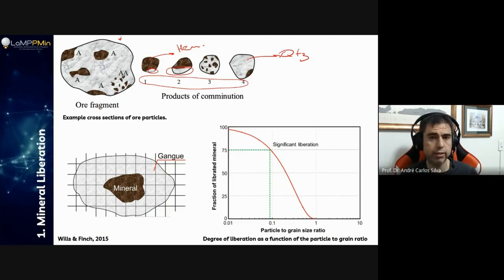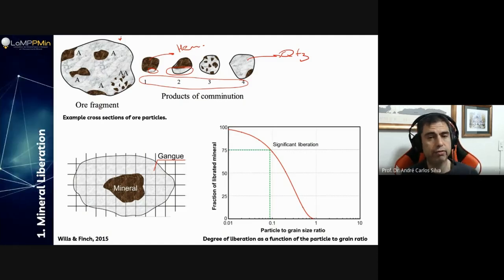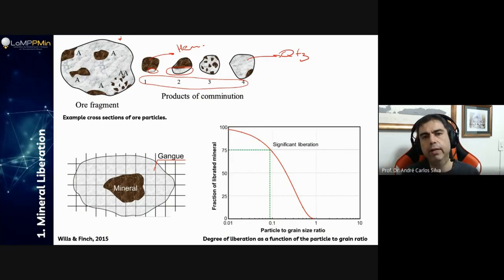But just take a look. This particle is not 100% hematite. And we're going to have this contamination in our final product. So that's the first thing we have to consider. It's virtually impossible to have a 100% hematite concentrate. We're always going to have a little bit of quartz in this concentrate. Why? Because we're not going to achieve 100% of all my particles only composed by hematite. We're gonna have different degrees of association, and this association is real, and it's quite difficult not to have this, okay? So let's go to particle number two.